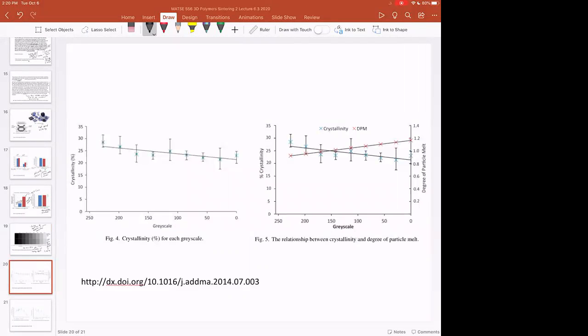And so in this nice paper right here, and this is from Neil Hopkinson's group, who was inventor of HSS, they're looking at the percent crystallinity as a function of grayscale. And so you see a slight variation in the percent crystallinity depending on how much fusing agent you put down, depending on the grayscale. And this is degree of particle melt right here. So they're showing, in effect, the degree of particle melting you're getting based on how much toner you're putting on there.